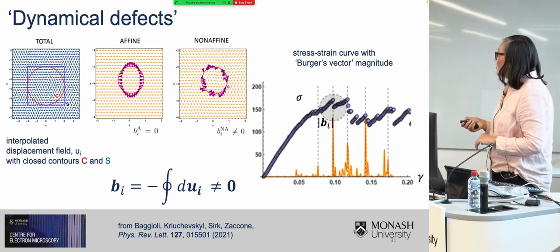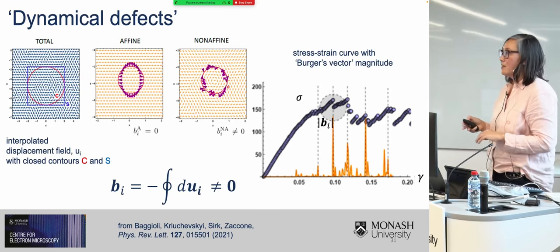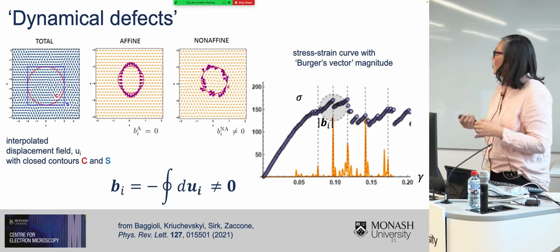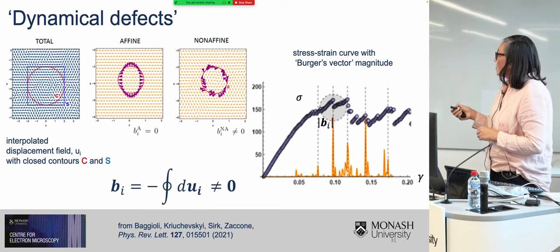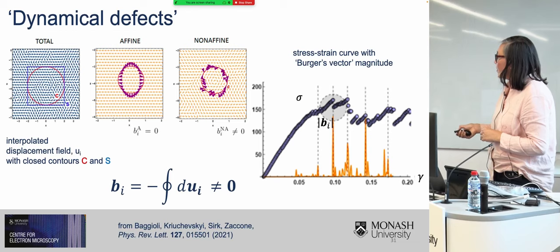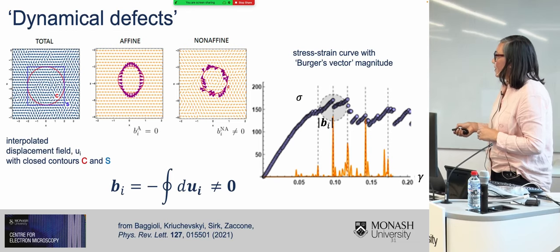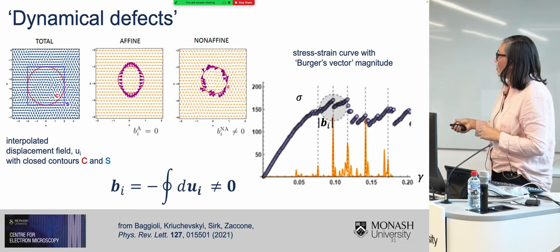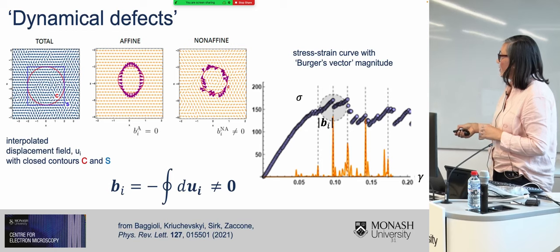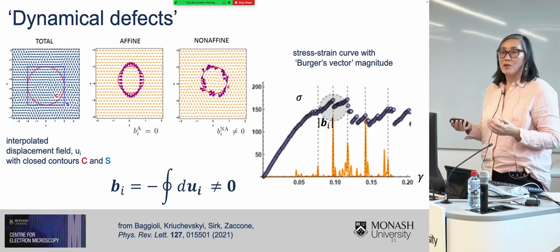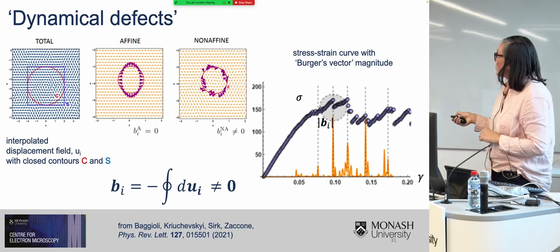And indeed, this group have suggested that these points are actually some kind of topological defect. So here they've defined a sort of Burgers vector, which you can calculate if you do a closed contour around different regions of your displacement field. And you can see that this Burgers vector here will only be non-zero if you have significant non-affine displacements.